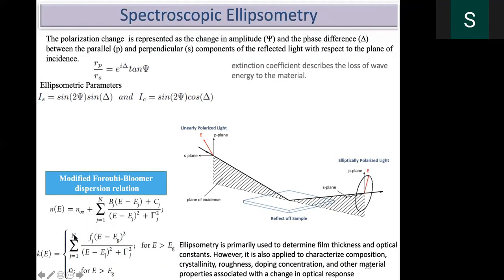Well, we have used spectroscopic ellipsometry. I'll tell you briefly, which is not my field but my collaborator's field. The polarization change is represented in the form of amplitude and phase difference, for the perpendicular component and the parallel component of the reflected light. If you analyze this, you can find out the refractive index of the material, the roughness of the surface, and the thickness of the film, because each and every layer can be studied when the light falls and reflects, and the layer thickness can be found out.